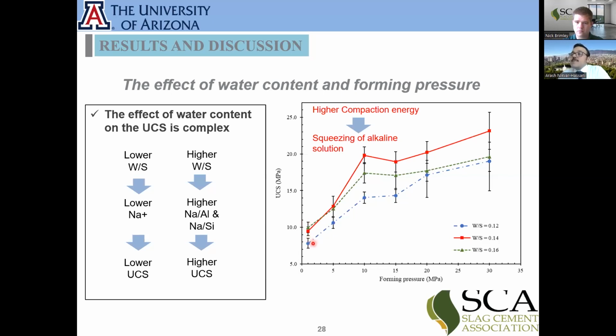But as we increase the forming pressure, if the water to solid ratio is too high, then during the pressure, the water is going to squeeze out, and you're going to lose your alkaline solution, and the UCS is going to be lower, which you see after 4 megapascal or 3 megapascal forming pressure. Then the liquid is starting to squeeze out, and the UCS is lower than at 14% water content.